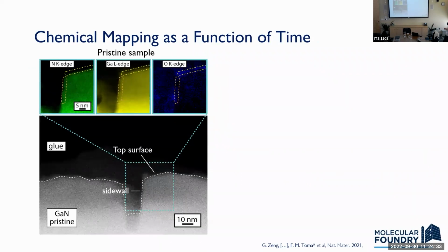We utilized scanning transmission electron microscopy, this time with a molecular foundry, that basically allows you to look at the material. So this is the gallium nitride layer. And we can look at the nitrogen, the gallium, and the oxygen edges to try to understand the chemical distribution. So in this case, on the side wall, you have nitrogen localized with gallium, and then oxygen is just not present. And then on the top of the material, you don't see nitrogen, but you have a layer of gallium that is oxidized because oxygen is bound to it, and that corresponds also to the XPS that I showed you earlier.